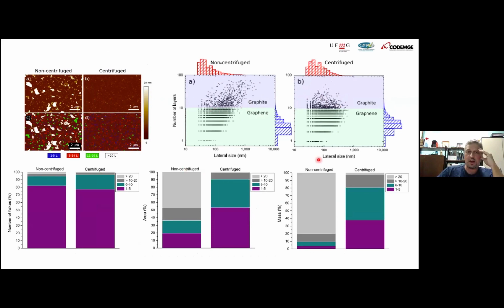If somebody shows you statistics of numbers of flakes, it means nothing. The amount of graphite is very small because you have very few flakes and you have very many tiny graphene flakes. You have to see this one here, or at least the statistics of area. All right, so this is the same pair of samples. Look at number, area, or mass. And another thing, true statistics is something more than 10,000. We have tested this a lot, and we know.